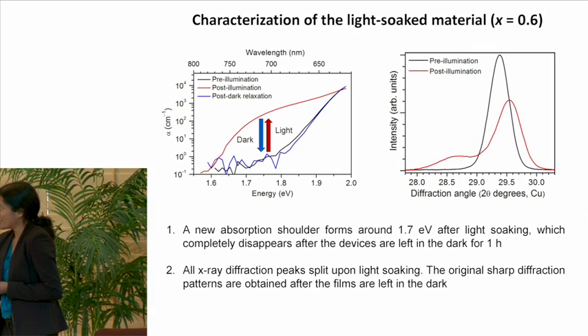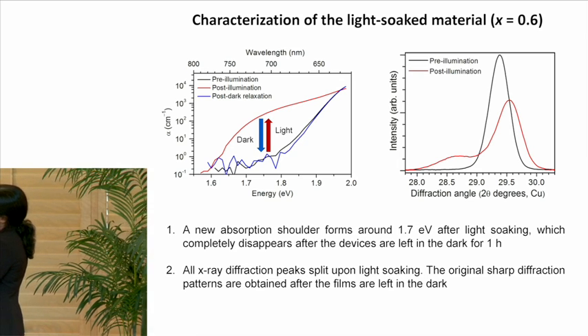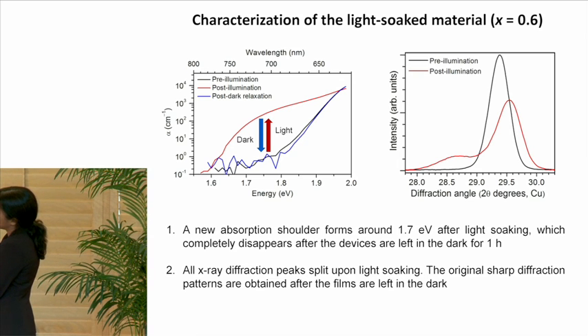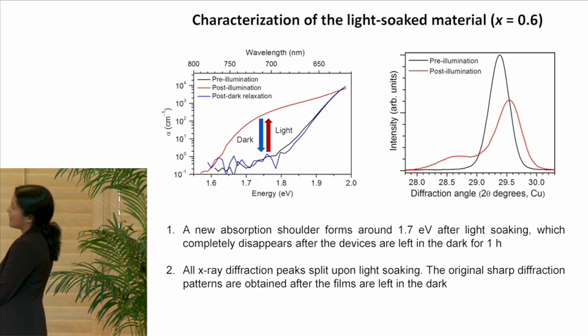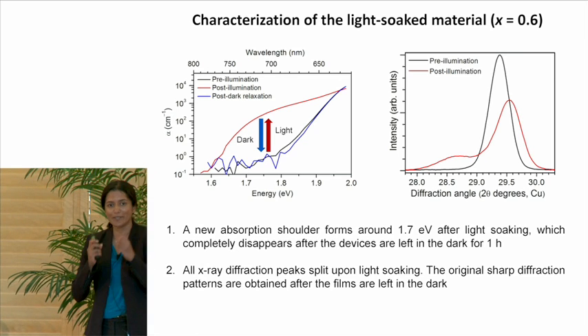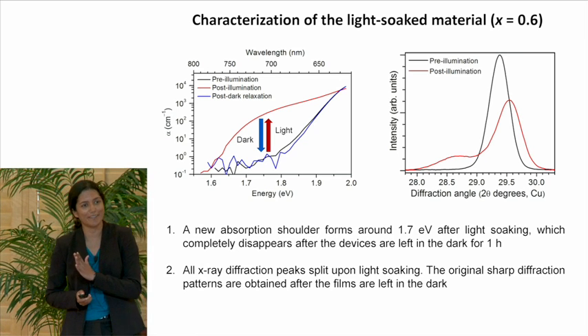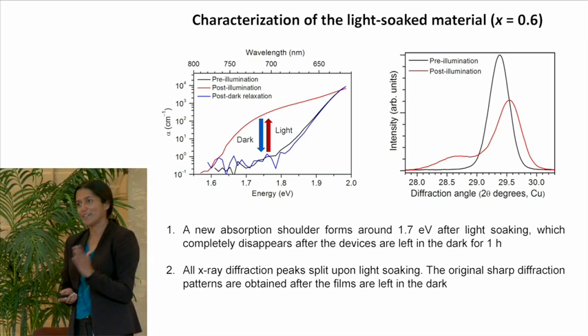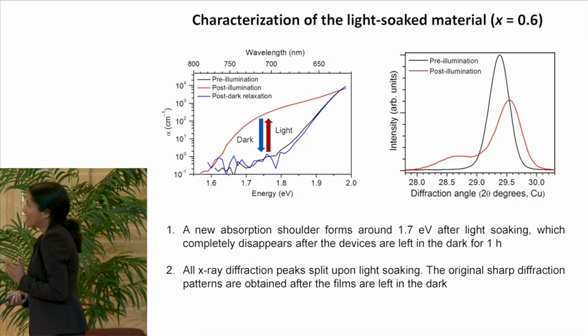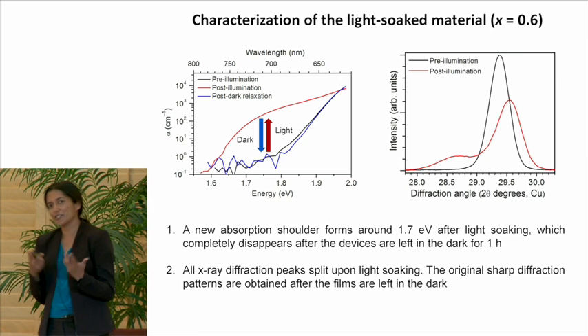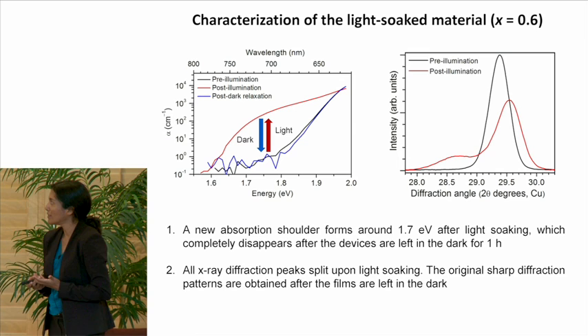And we did several experiments. So here Eric sees that under illumination, a new sub-bandgap shoulder grows in at around 1.7 eV. And again, when the light is turned off, the shoulder decreases. Light is turned on, the shoulder grows in, and so on. This can be cycled. And Eric then wanted to study the structure of this material under illumination.